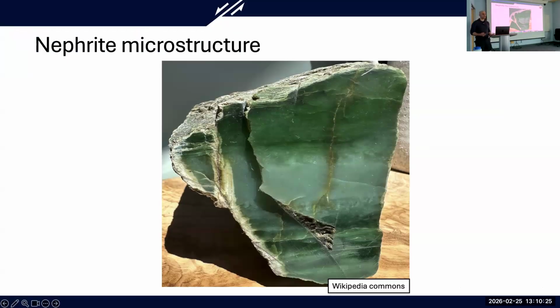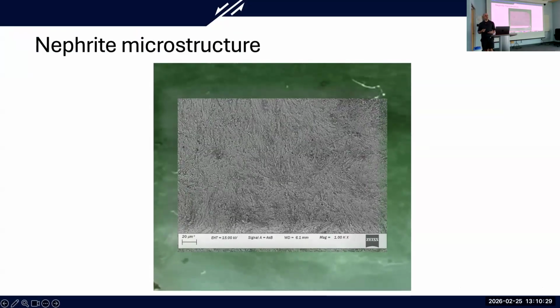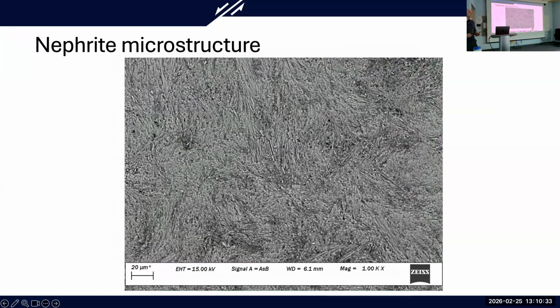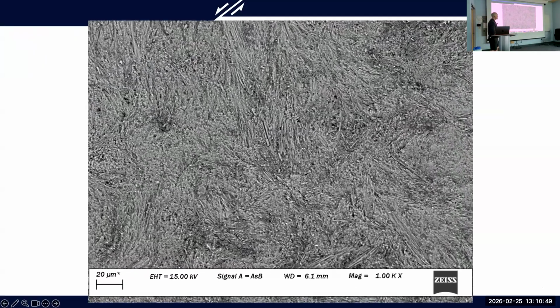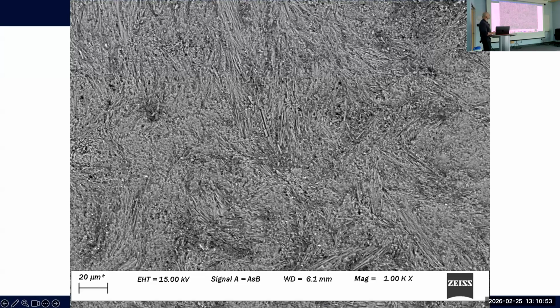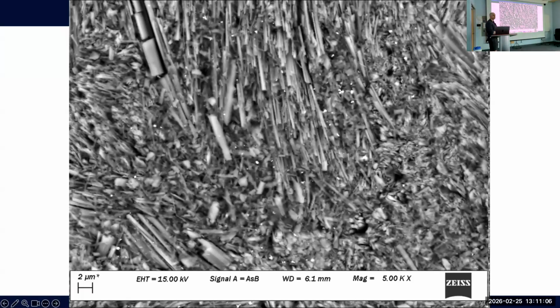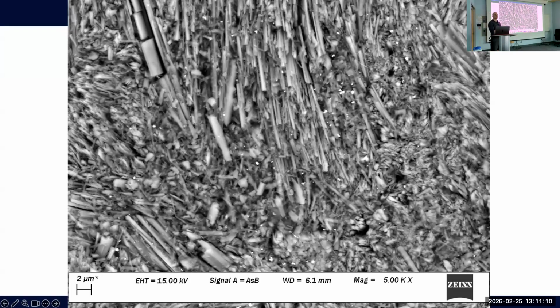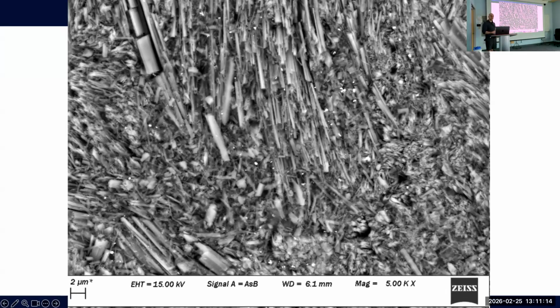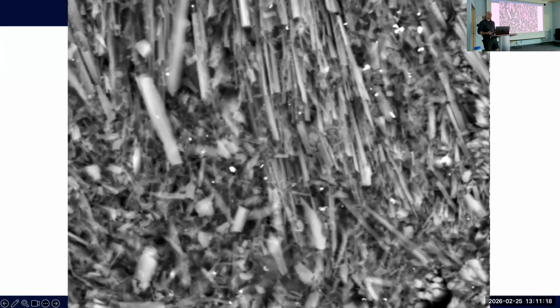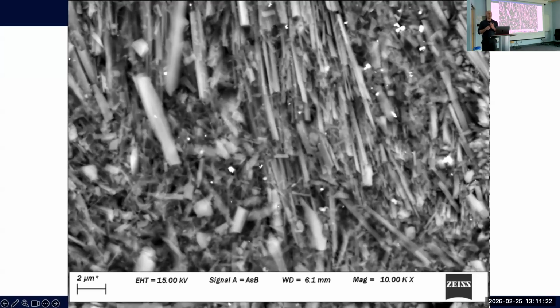So here we have a lump of nephrite jade. If we zoom in, we obviously don't see very much, but if we use something like an electron microscope, here we're looking at a secondary electron scanning electron microscope image, and we can begin to see what it is that gives rise to that incredible toughness that we'll be looking at in a moment. Here we can see those individual amphibole needles, and if you look closely, they've all got variable orientations. They are all tightly packed. They come in clusters where within a single group, they might be well oriented, but you can see a range of orientations present throughout. And so if you imagine a fracture that has to propagate through this, if it's propagating along grain boundaries, it's not going to go very far until it hits another mineral and has to deflect.